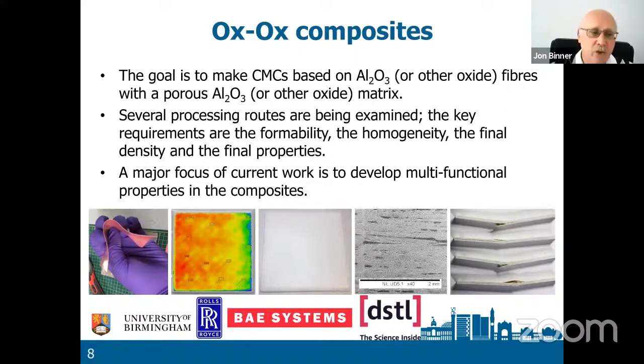And you've got a small number of illustrations there. Bottom left-hand corner, you've got a nice purple glove. The main thing about that is a fabric layer, and you can see how easily bent and deformed it is. These are not stiff materials until after they are fired. Then you've got a thermograph. What that does is you apply heat suddenly to the surface of the material, and then you look at the residual temperature, and it tells you a lot about the thickness of the layer and any flaws or problems you have got in the system.